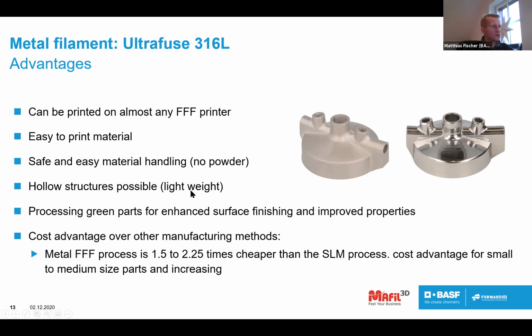You can print hollow structures like you know it from the FFF printing process in general. And afterwards, you have a so-called green part, which means you have a polymer part with a very highly filled metal powder inside. You can also post-process this part, like grinding or polishing, before you give it to the following debinding and sintering process, which is necessary to get the metal properties afterwards. It can also have cost advantages over other methods.